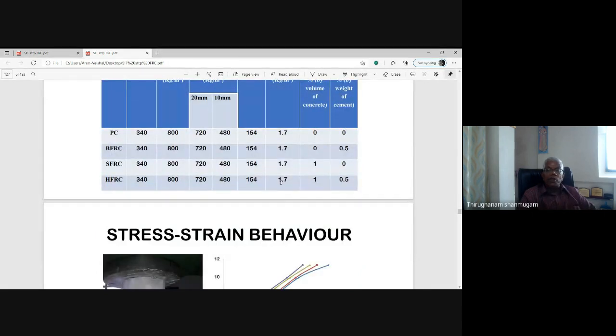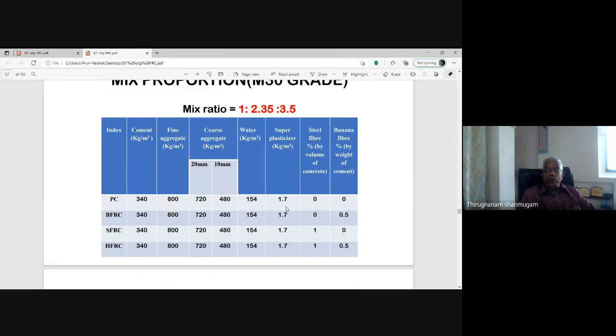This is done by using IS 10262 code of practice. The superplasticizer is used as 1.7 kg per meter cube, that is 0.5%. And the steel fiber initially 0, banana fiber is 0.5% by weight of cement. Steel fiber is by volume of concrete, SFRC 1% by volume of concrete, and HFRC 1% and 0.5%. So banana fiber, steel fiber, and hybrid fiber.